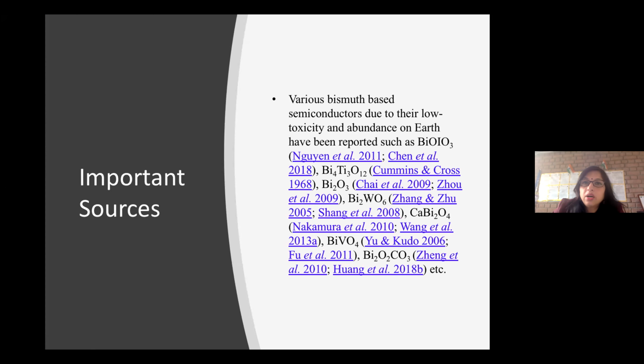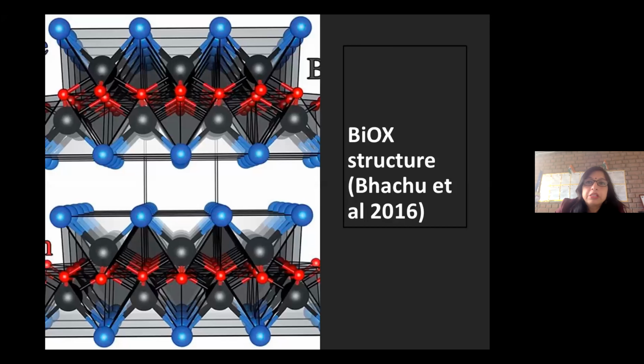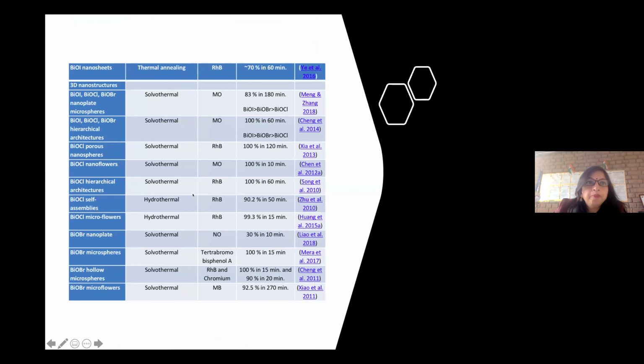The materials which are helping in this direction are bismuth based materials. There are many materials, but here I'm taking bismuth oxyhalides. When we see the structure of bismuth oxyhalides, the bismuth oxide ions are interleaved by double slabs of halogen atoms. The blue ones are halogen atoms. They make dipoles and enhance the separation of electron hole pairs. So the first thing is the bismuth oxyhalide structure is of that type which solves the problem and can lead in the direction of better photocatalysts. So we will see the results then.